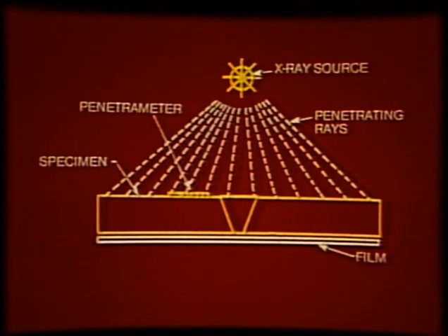Radiographic inspection of welds is done in a similar fashion, either with X-rays or with radioactive material called isotopes, which generate higher energy gamma rays. In addition to providing data for a more exacting evaluation, it also provides a permanent record in the form of a photographic image, or radiograph. As the radiation passes through the test item, the indication of the flaw shows as a lighter or darker area as compared to the surrounding metal.